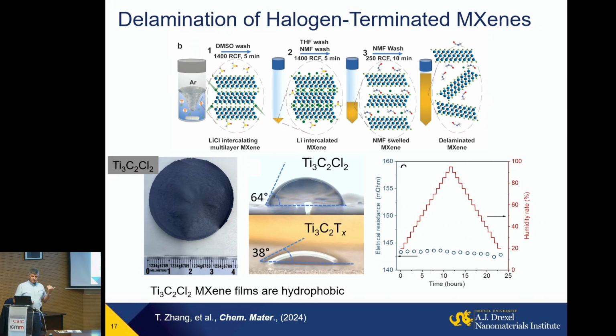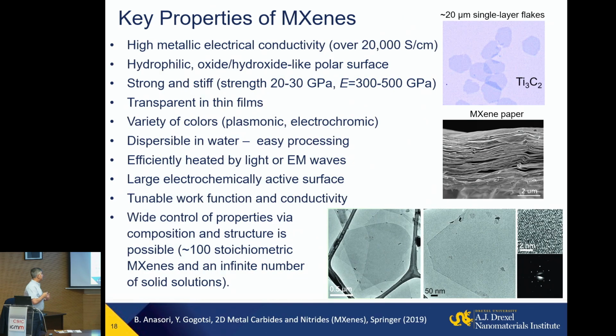And of course, chlorine terminated MXene, for example, will be different. It will be hydrophobic. So you will have to disperse it in non-aqueous solvents like THF, NMF. You can actually transfer it after that to isopropanol, but it's hydrophobic, it doesn't imbibe water. It has its own advantages, so if you're looking for a hydrophobic film, you again can do it. Now, it's great to have a potentially infinite number of new materials made from abundant precursors in highly scalable processes, processed from pure water without anything added.